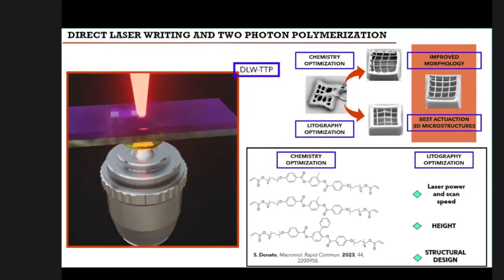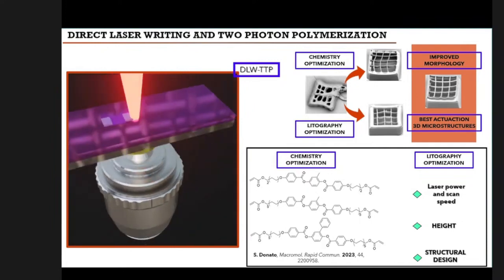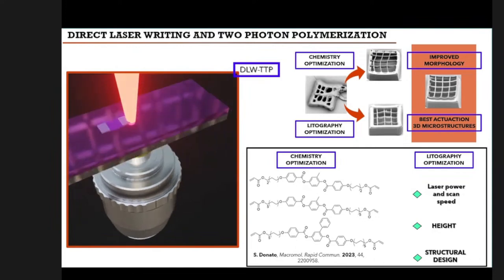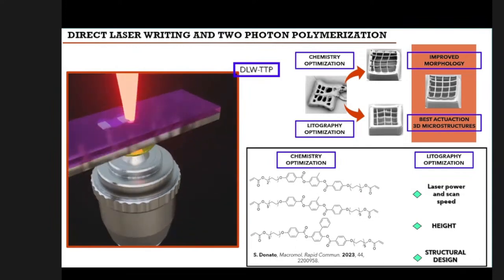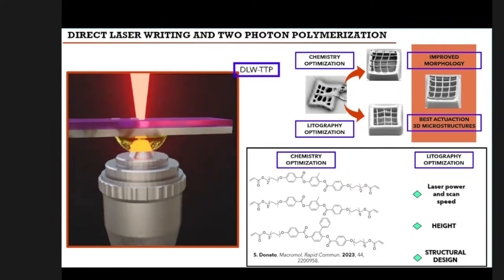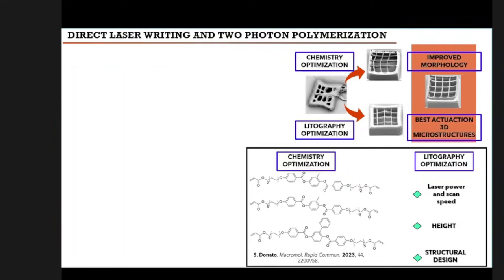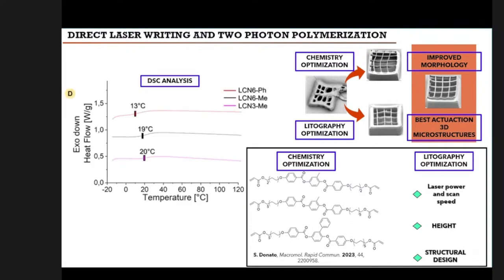So for the chemistry optimization, I propose the use of different monomer mixtures based on different cross-linkers, which possess different substituents in the liquid crystal core. Because, as I previously stated, the substituents in the cross-linkers are a powerful tool to obtain huge modifications in the thermal, mechanical, and also actuation properties of the final materials. As you can see from the DSC trace, using a phenyl group in the liquid crystal core of the crosslinker, I was able to obtain a decrease in the glass transition temperature of the final material.